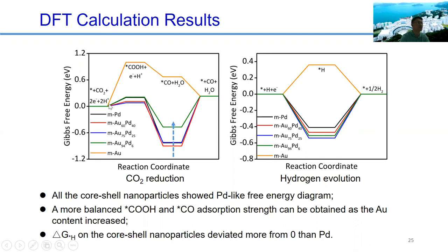And this is the reaction coordinate for the CO2 reduction, and this is for the hydrogen evolution. You can see that for gold, the first step is too slow, and for palladium, the last step is too slow. This is the removal of the CO, and for gold it is the adsorption of the CO2. So you have to create a kind of balance, right? And you can see clearly for this green one, gold 94, palladium 6, the first step activation energy is quite low, and the last step, compared with pure palladium, is also significantly lowered. So this is why the gold palladium catalyst gives you better performance.